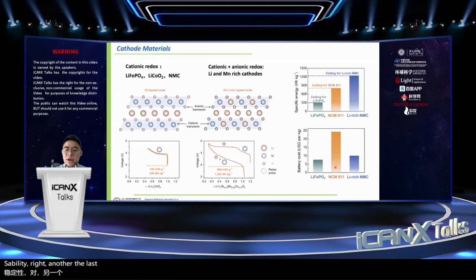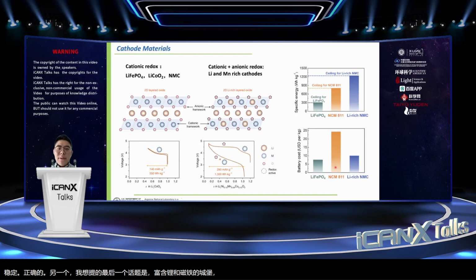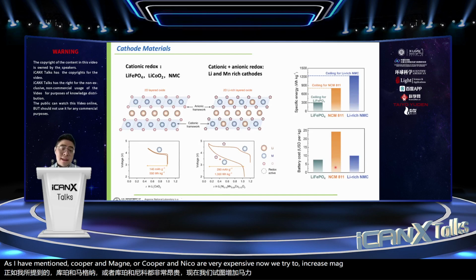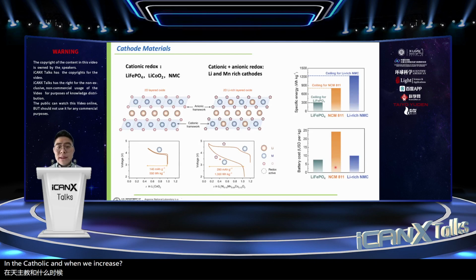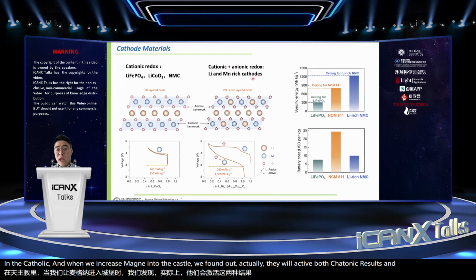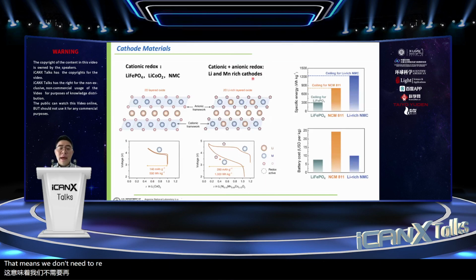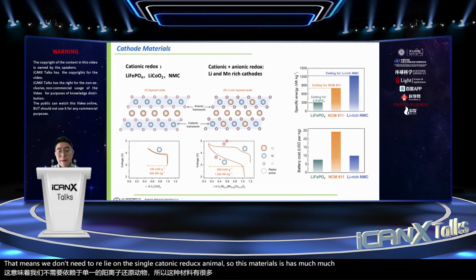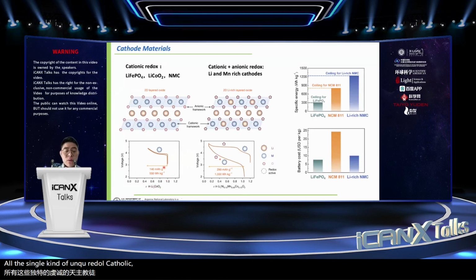And the last topic I'd like to mention is the lithium and manganese-rich cathode. As I have mentioned, cobalt and nickel are very expensive now. We try to increase manganese content in the cathode, and when we increase manganese, we found out they will activate both cationic redox and anionic redox. That means we don't need to rely on the single cationic redox anymore. So these materials have much higher capacity. The conventional single cationic redox cathode has only 140 milliamp hour per gram. However, these materials can deliver double the capacity.